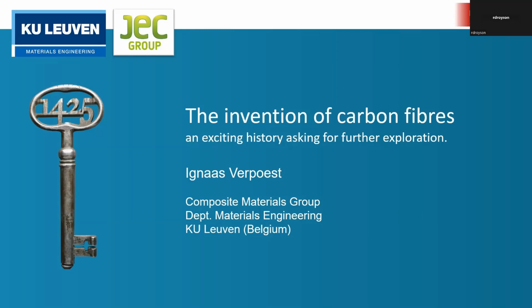So yes, it's interesting to have lignin as a precursor, but the fact that after 10 years we still do not reach the same properties makes me doubt a little bit whether we ever will be able to do that. And hence the door is open for other innovations. So why not try to make polyacrylonitrile precursor fibers based on bio-based chemicals, so that the process has a lower environmental impact. Although not all the problems will be solved then, and I will come back to that in my second lecture, because the process of polymerizing acrylonitrile and spinning the fibers is in itself, irrespective of whether it's a bio-based chemical or not, rather energy intensive and CO2 intensive.